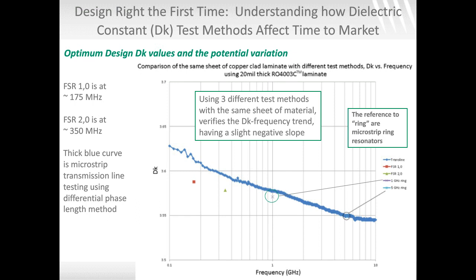Then I sent that panel off to have circuits made, and some of these circuits were ring resonators. The 1 gigahertz ring resonator had a higher dielectric constant than the 5 gigahertz ring resonator. Again, the trend was verified. And then, of course, the thick blue curve there is the microstrip transmission line's differential phase length method, and you can see that an increase of frequency decreases the dielectric constant. So that general trend I showed on the previous chart of the material dispersion appears to be correct. And we have tested this many times in the past as well.